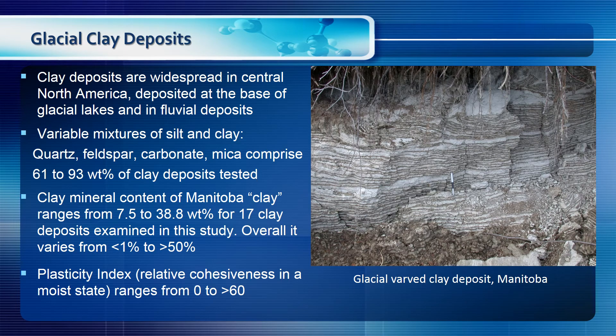We can now turn our attention to the nature of clay deposits available for construction. Clay deposits are widespread in central North America, deposited at the base of glacial and other lakes and in fluvial deposits. They are comprised of variable mixtures of silt and clay; the silt component is largely quartz, feldspar, carbonate, and mica, and made up 61–93 weight percent of the clay deposits tested in this study. The clay mineral content of Manitoba clay ranged from 7.5–39 weight percent for the 17 deposits examined. Overall, clay minerals make up less than one percent to greater than 50 percent of clay deposits.